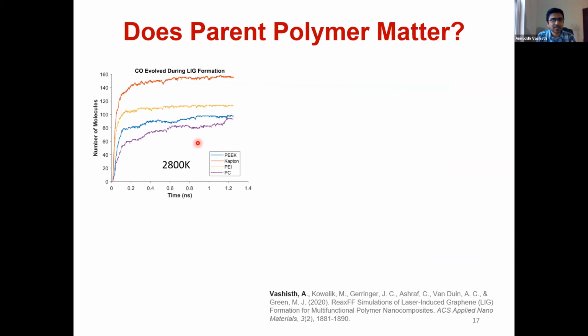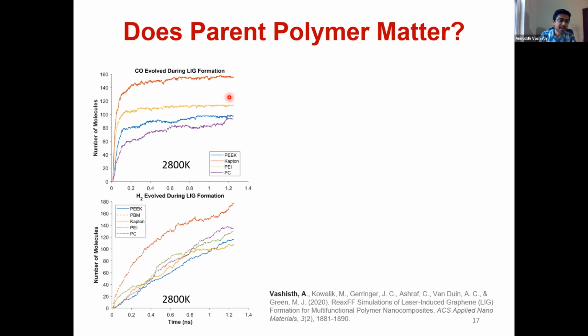We also looked at what are the different gases that are getting evolved. So for example, at 2800 Kelvin, if we look at CO, carbon monoxide that is getting evolved, you see that Kapton releases CO. And this is mainly because Kapton has a higher content of oxygen in it. And one of the reasons why you see such a foamy structure is because there's a lot of gas evolution as well. We also looked at H2 evolution, how much hydrogen is getting evolved. And basically the evolution of hydrogen is contributing to conversion of sp3 carbon to sp2 carbon.